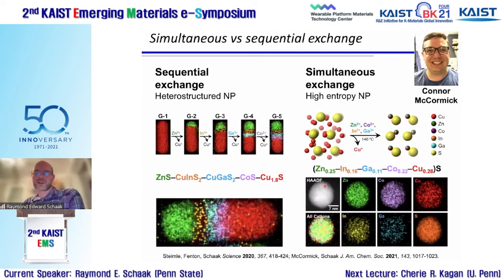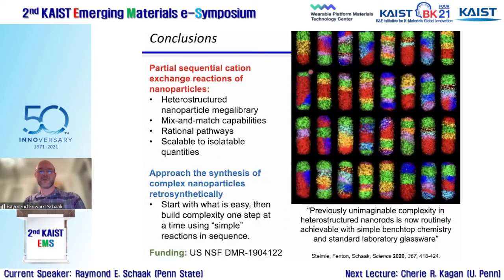When you do that same reaction with a simultaneous injection, meaning all cations are present together in solution applied to spheres, they end up forming a high entropy metal sulfide. They end up forming a solid solution. They don't segregate, they all intermix. And so that's another cool thing that comes out from design space, being able to tune between solid solutions and heterostructuring based on the morphology and the way that the exchange is done, whether it's sequential or whether it's all together in one.